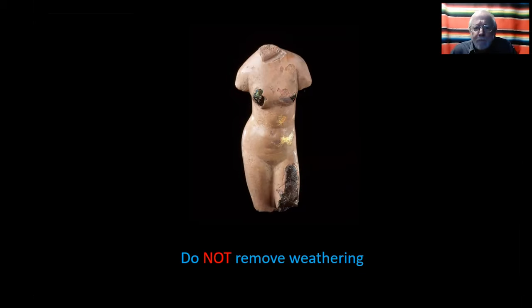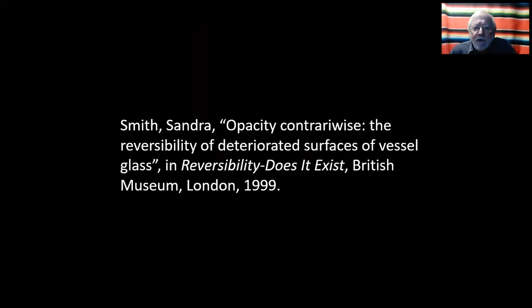So if you remove that weathering, you're removing layers of original glass, including the original surface. So we really do not do this. And it leaves you behind, as you can see on the thigh there, a really pitted, uneven surface, because the weathering doesn't always form absolutely solid layers. There's a good article on this by Sandra Smith called Opacity Contrariwise. I think that's a great title. It comes from the conference that was held at the British Museum in 1999. And it talks about people who've argued that you should take it off or should not take it off and what you are taking off. But in my mind, the main thing is it's removing some of the original surface. And as we know, the silica is basically the most stable part of the glass. So you're also removing a generally protective surface.